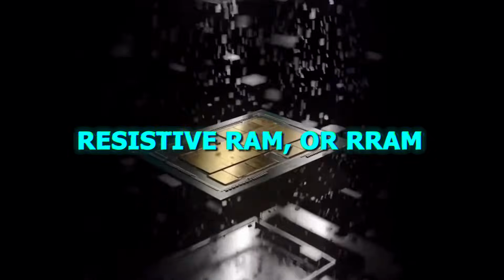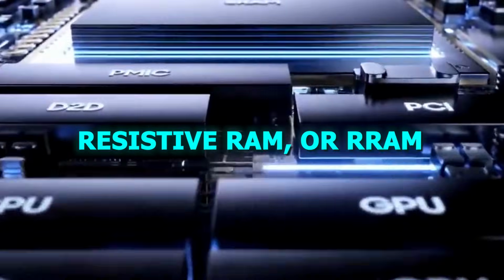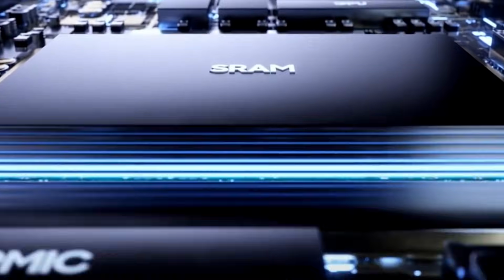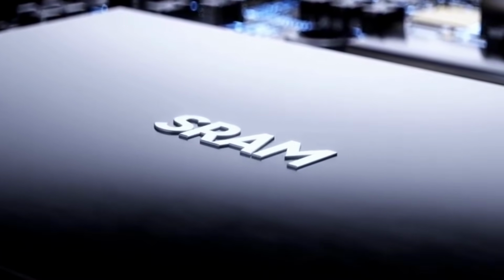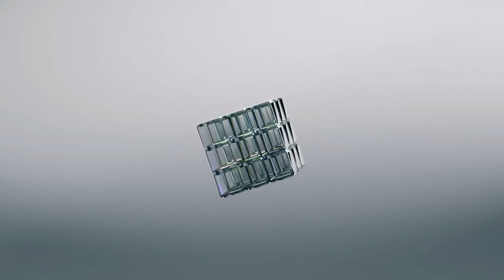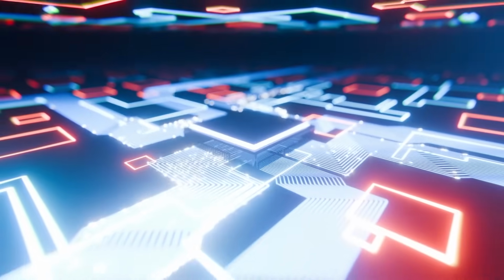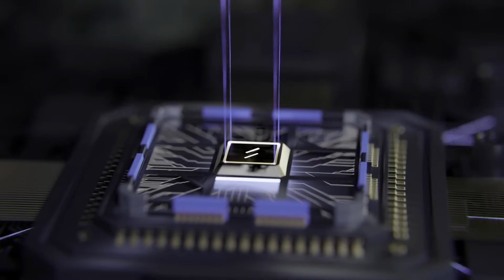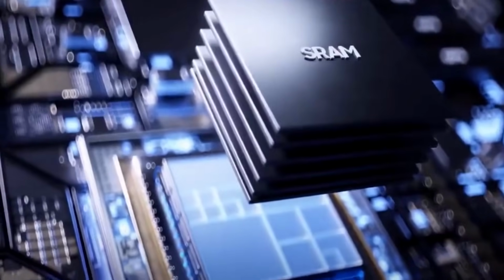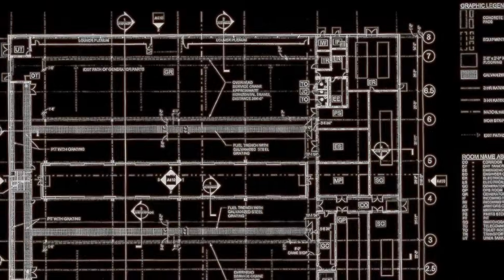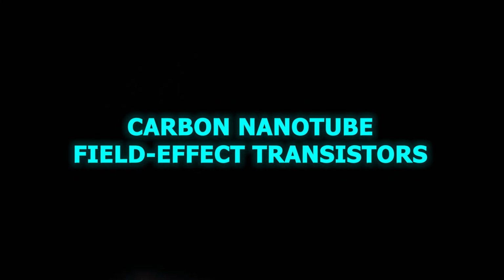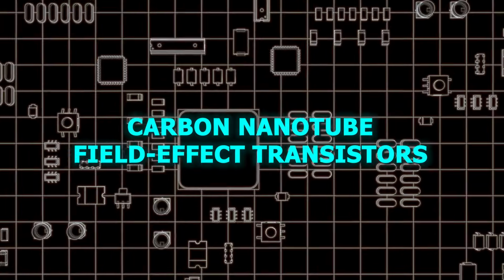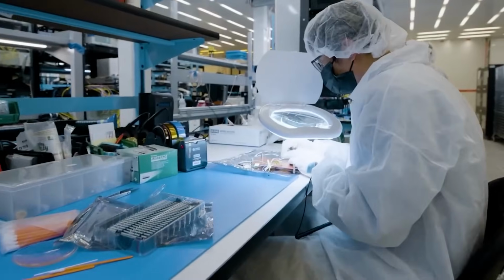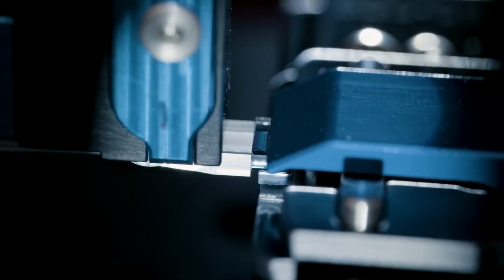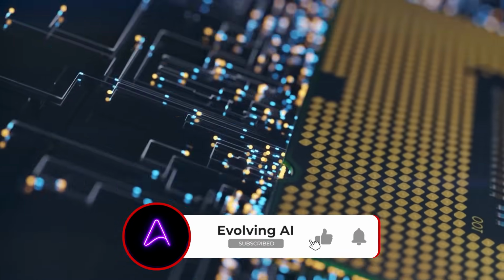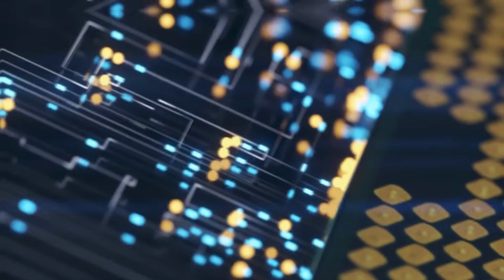Memory layers can be built using resistive RAM, or RRAM, a non-volatile memory that stores information by changing resistance rather than charge. RRAM is well suited for vertical integration because it can be fabricated at relatively low temperatures and placed directly above logic layers. Similarly, advanced logic layers increasingly explore transistor technologies beyond traditional silicon CMOS, including carbon nanotube field effect transistors, CNTFETs, which offer strong potential advantages in energy efficiency and are compatible with low temperature fabrication, making them ideal for upper layers in vertical stacks.